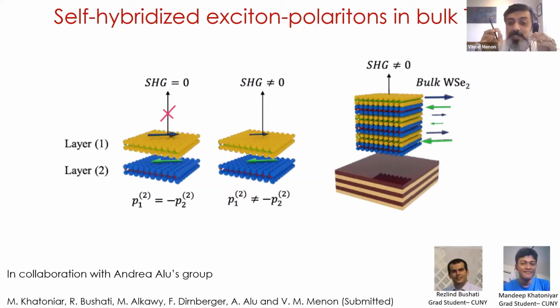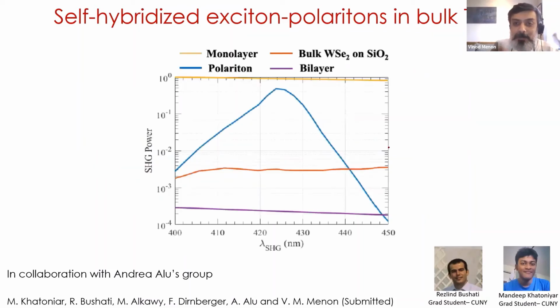electromagnetic field, and hence although the whole bulk is centrosymmetric, the fields don't cancel out because of the phase accumulation at each layer. And the result of this is that if you take a bulk material in a polariton regime, you can get a large increase in the overall second harmonic signal. So in some sense, what we have done is we have relaxed the rule for nonlinear optics through the strong coupling, where the strong coupling or the field associated with strong coupling essentially changes the phase accumulation at each of these individual layers. And so these layers act as if they are individual systems, and they add up to give you a net second harmonic signal.